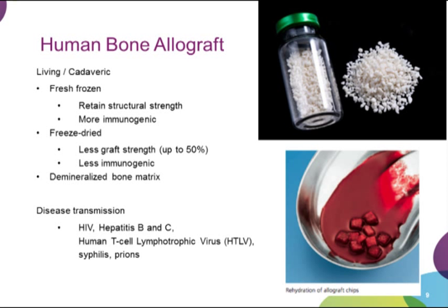The VIFM uses tissue which is fresh frozen, or freeze-dried. I've looked at American data, and freeze-dried tissue can be stored at -20 or -70 degrees, but here we actually do it at -80 degrees. When it's stored at -20, the shelf life is only 1 year, but at -70 or -80, it's usually up to 5 years, and we keep bone here for 5 years.